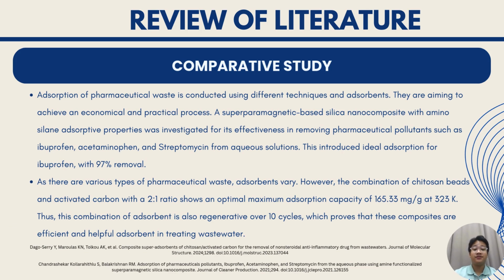Next is the comparative study of different adsorbents. First, a study that used superparamagnetic-based silica nanocomposites functionalized with aminosilane as their adsorbent has shown high efficacy in removing pollutants like ibuprofen, acetaminophen, and streptomycin, achieving a 97% removal rate for ibuprofen. Another study has shown that a 2 to 1 ratio of chitosan beads and activated carbon has demonstrated a maximum adsorption capacity of 165.33 milligrams per gram at 323 Kelvin. This composite is also regenerative over 10 cycles, proving to be a sustainable and cost-effective adsorbent.